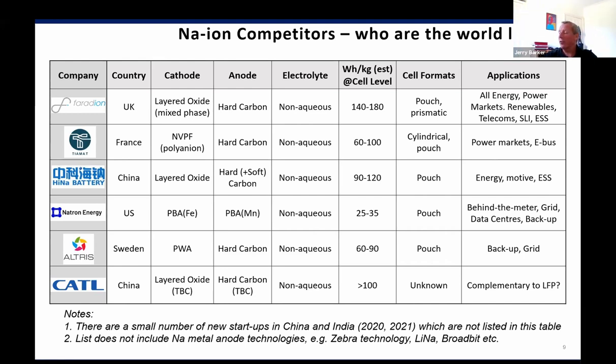Altris in Sweden are an interesting one in that they're probably the most recent company to enter this space. They're a spin out of Uppsala University. Again, we know these guys well, and they've taken a slightly different tack as well, where they're using Prussian white analog on the cathode side, hard carbon on the anode. And because of that, they're running at a specific energy of 60 to 90 watt-hours per kilogram. And they're targeting backup and grid applications, stationary applications.